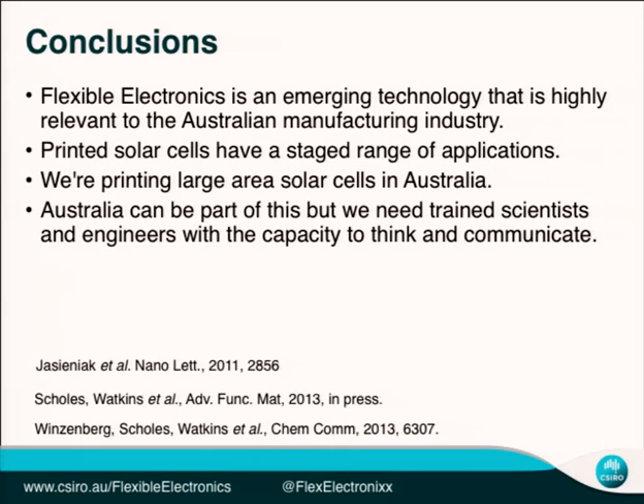In terms of the roofing with BlueScope, how do you envisage attaching it to the roof, or is it a separate adhesive on the back, like two separate materials? They've actually got a lot of experience with glues that will stick to their roofing material. Ideally, you would make it in a continuous laminating process as part of the steel production. So they would make it in situ then? They would ideally like to do that, but if not, you make it two separate things and you glue it on. And they know the properties of their steel well enough to know glues that are going to stick on there for 20 years. But differential expansion in heat and cold creates a major problem with most glues. They are a little risky to use for that reason. I think in that case I just defer to their expertise. They've got a setup in Wollongong where they've had it for about 2 years now, and they're measuring that.